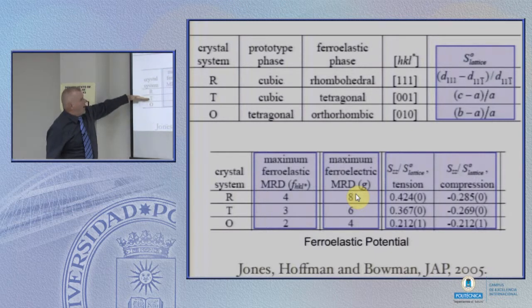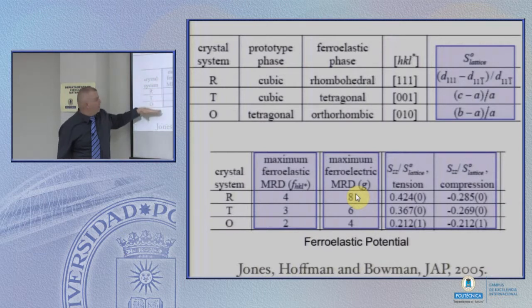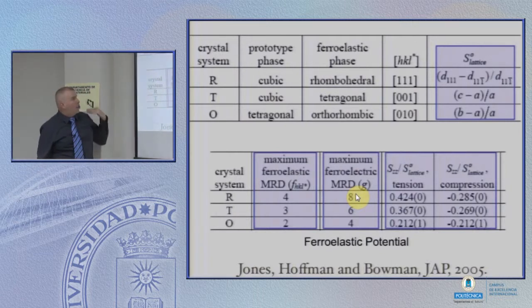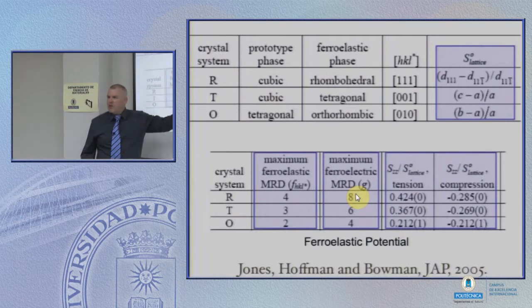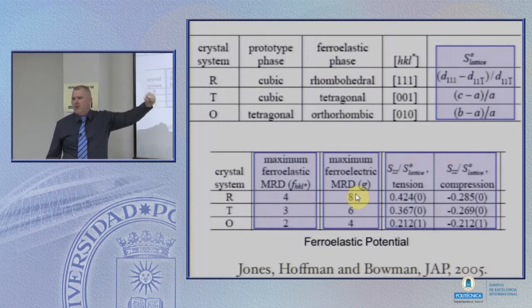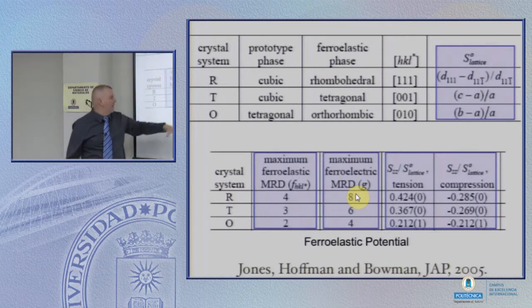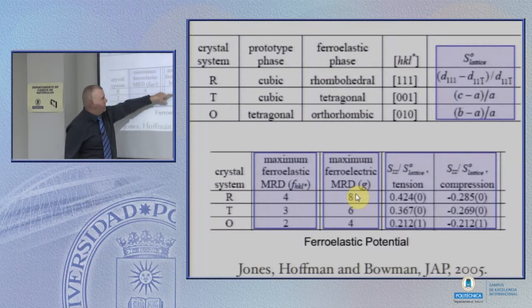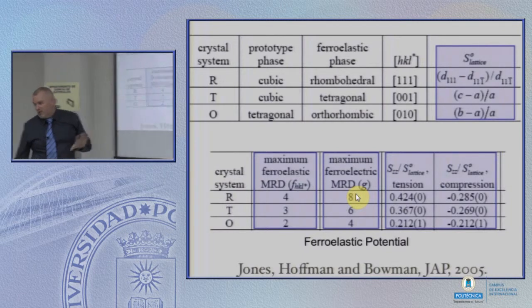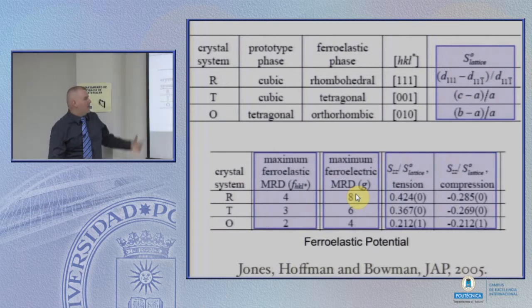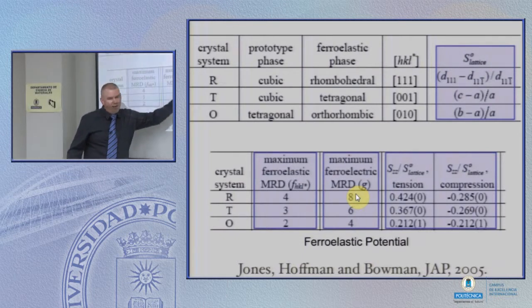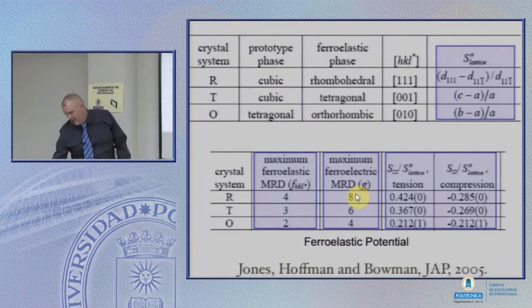for tetragonal, as I said, is 3. For rhombohedral, there are 4 possibilities. And for orthorhombic, there are 2 possibilities, because you're usually just switching between A and B. Okay, so the maximum value for this is 4, 3, or 2. If we include the polarization, the plus minus part, which is usually a different measurement, it's essentially twice that. So there's 8 possibilities, 6 possibilities, and 4 possibilities based on the crystal structure. And from that, you can evaluate the possible strains and many other things that can take place in those materials.